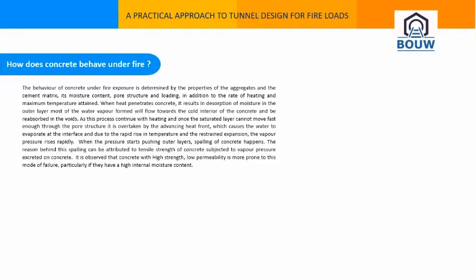As this process continues with heating, once the saturated layer cannot move fast enough through the pore structure, it is overtaken by the advancing heat front, which causes the water to evaporate at the interface, and due to the rapid rise in temperature and the restrained expansion, the vapor pressure rises rapidly. When the pressure starts pushing the outer layers, spalling of concrete happens. This spalling can be attributed to the tensile strength of concrete being exceeded by the vapor pressure exerted on it. It is observed that concrete with high strength and low permeability is more prone to this mode of failure, particularly if it has a high internal moisture content.